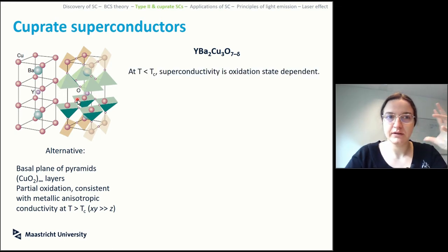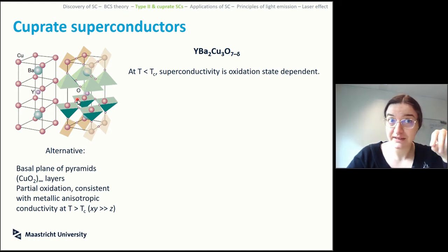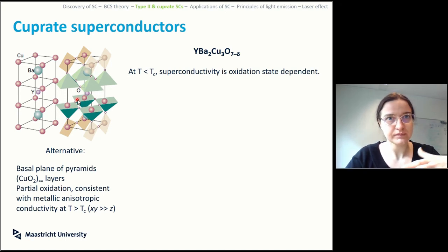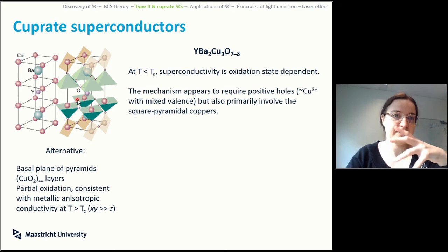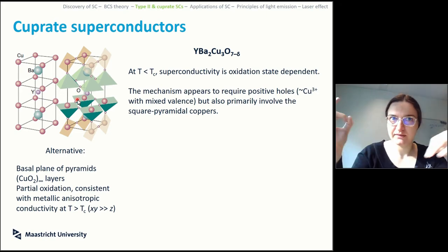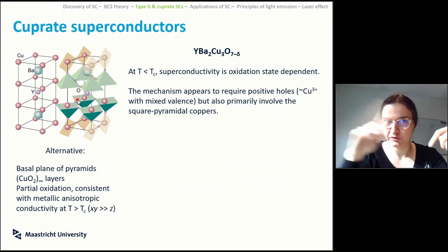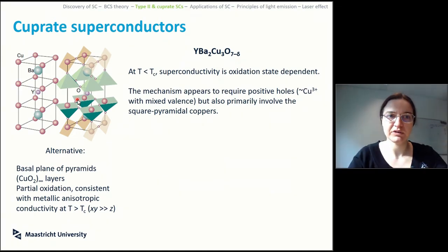So basically with this thing, you know that the oxidation state is your trick of giving electrons to bring around, and the more oxidized part has this copper oxygen bands that actually give the conductivity, and you can have a charge transfer, so this electron can actually jump in the pyramids and possibly out of the pyramids into the square planar unit. So it kind of looks like a positive hole thing, because you have this empty possible orbital in which you can actually make the thing jump around, but it primarily involves this thing.